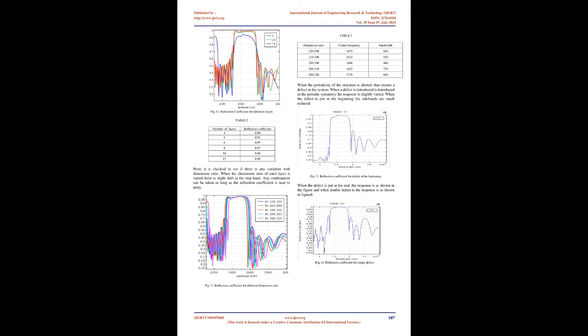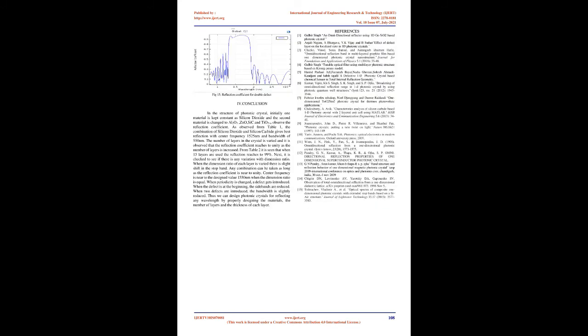The different materials taken are Al2O3 with refractive index 1.76, ZnO with refractive index 1.92, SiC with refractive index 2.55, and TiO2 with refractive index 2.65. The combined result of reflection coefficient is as shown in the figure. The center wavelength which is selected is 1550 nm, which is optimum for optical communication. So the structure can be used as a switch or reflector in optical communication. The following table gives the center wavelength obtained from the graph for different combinations and the corresponding bandwidth.